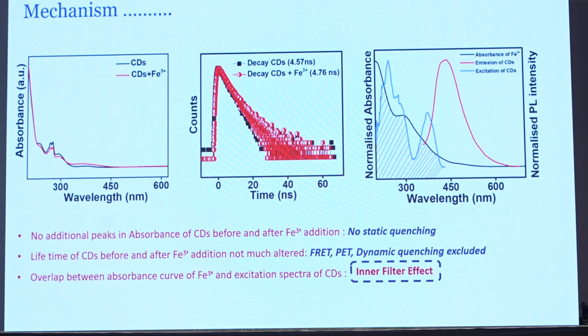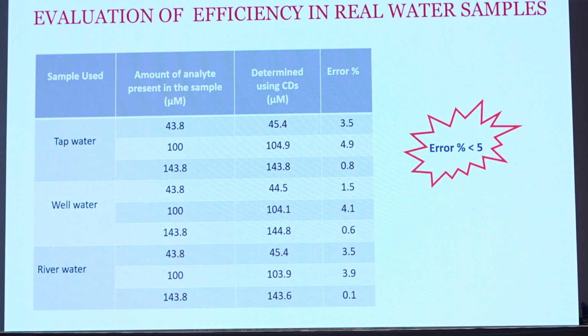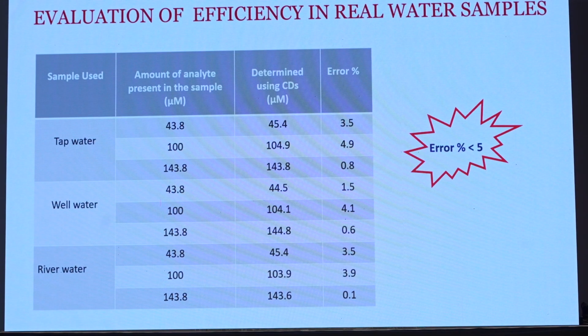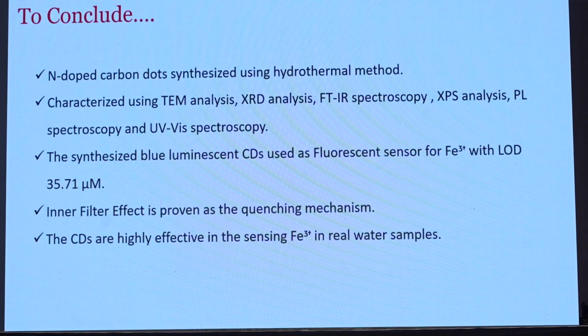Let's move on to the next analysis. We can see that the absorbance of ferric ion overlaps very much with the excitation spectra of the carbon dot. Thus, in our case, the quenching mechanism is due to the inner filter effect. Now we have analyzed the efficiency of the synthesized carbon dot in real water samples, and we obtained results with error less than 5%. Move on to the conclusion.